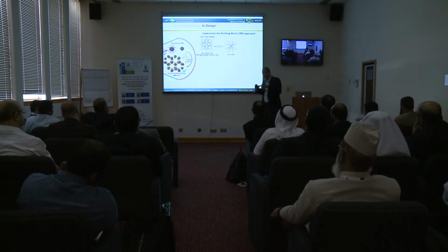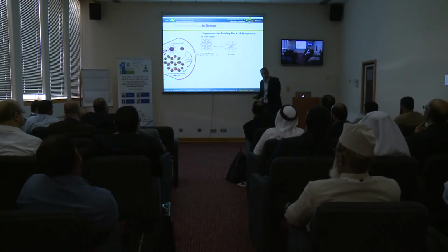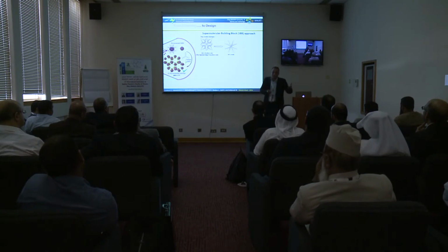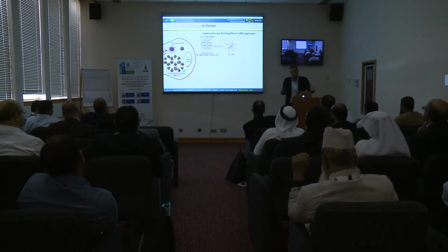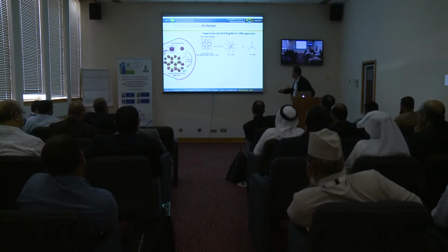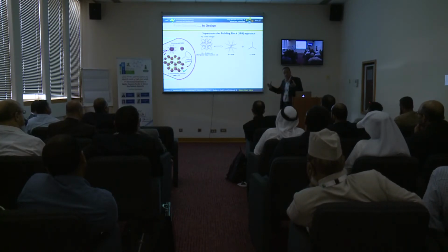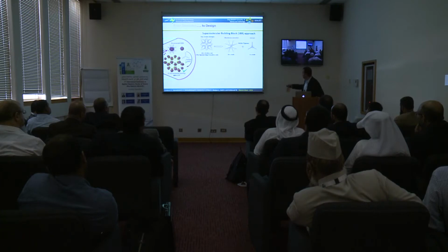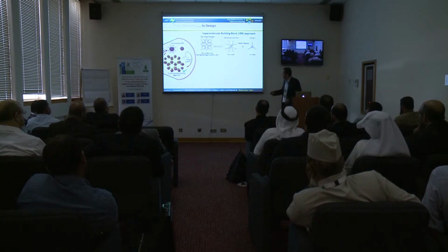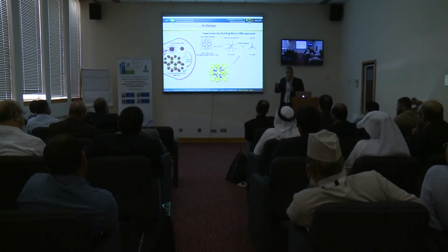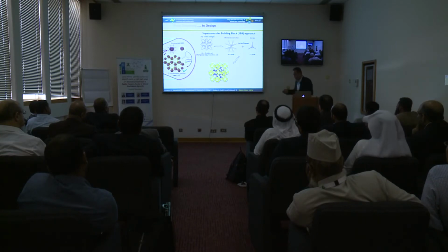So we didn't wait for that. We said, you know what? We need to find how we expose these 24 carboxylates outside without spending so much time to find this cluster. We're still looking today, and we don't have that cluster. So normally when you have your network, what you do is you augment the vertices, meaning you look at the geometry of your vertex figure. Like here you can see that this node should have this geometry and shape, and this should have this shape. If you have those two shapes, you link them together, and Omar Farha can witness that, you always get this structure. Unless you do something where you have flexible ligand, then you get layers. But generally speaking, you get this structure.